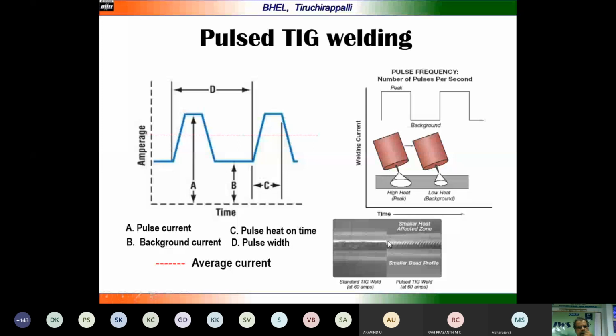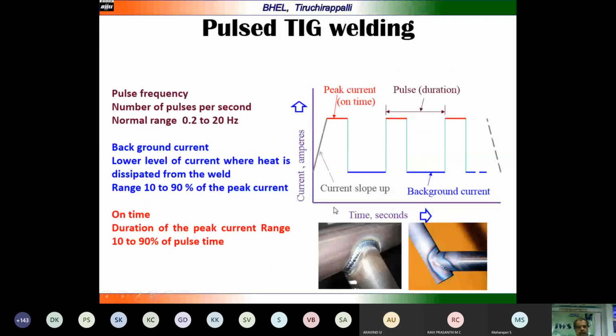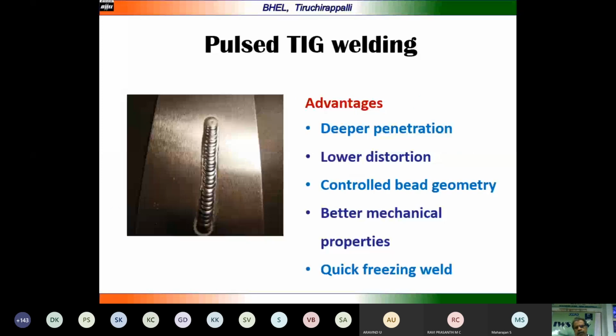In pulsed TIG welding, the number of pulses will be in the range of 0.2 to 20 hertz. The background current is a lower level of current where heat is dissipated from the weld, in the range of 10 to 90 percent of the peak current, and the on time can be set, and we can vary the parameters, then we can get very good welds using the pulsed TIG welding process. Advantages: deeper penetration can be achieved because we can go to a very high peak current for a smaller time and the metal can be deposited, and lower distortion because the total heat input is very low, and bead geometry can be controlled very easily, and because of the low heat input, the mechanical properties are much better than the conventional TIG welding process, and the weld can be frozen very quickly, and solidification can happen easily.